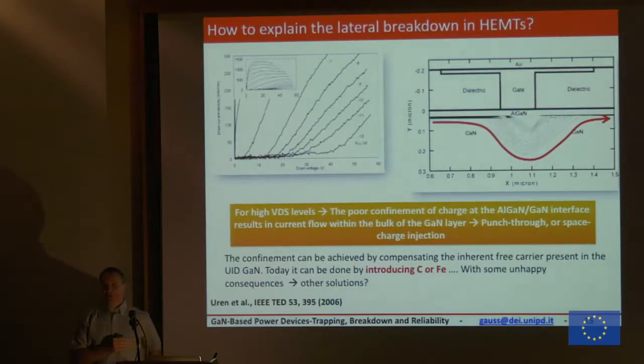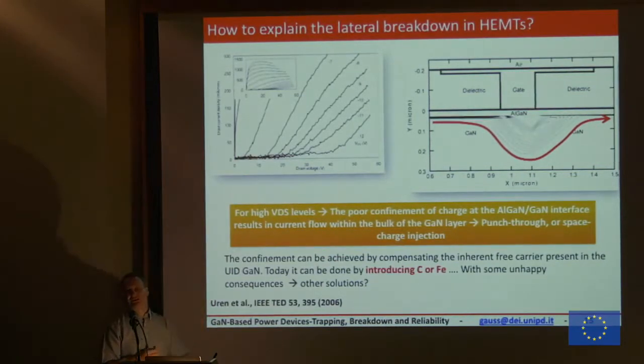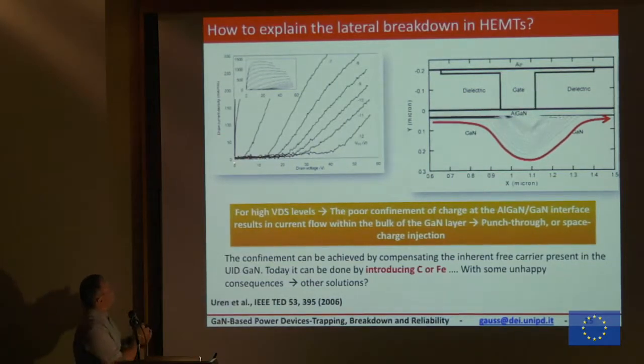Punch-through is one of the important problems for gallium nitride. So let's say that I have my device, okay? And as has been said yesterday and the day before, these are normally-on devices. We may speak about normally-off, but the situation is not that different. So they are normally on. So what I do, I give a negative bias to the gate, and I try to close the channel. So the channel is depleted. And if that is the case, I should not see any conduction current. But if I do my plot, what I see, in fact, for negative gate bias, is that the current is low, but at a certain point, it starts to increase.